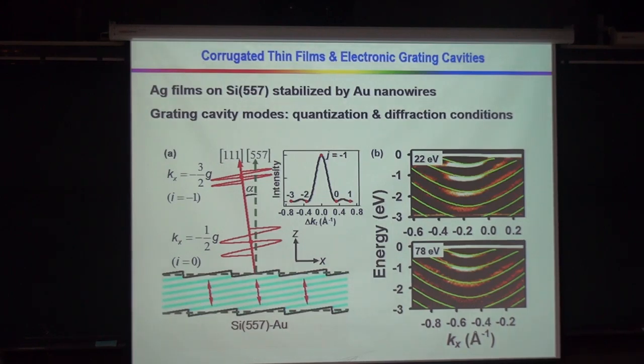Then you will have a stepped surface. So every now and then you will have a step missing one atom. So when you replot it, you got a step surface on the substrate. This actually happened with silicon 557 coated with gold, so you got this step surface. And then when you deposit film, you got film which has the same thickness, except you also got these steps. And so you got a diffraction grating here, you got a diffraction grating here.